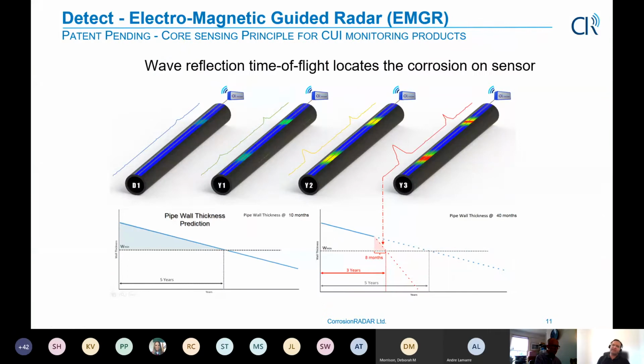The principle, as I mentioned, is electromagnetic guided radar, EMGR. It's a patent pending technique where the core sensing principle is, if you see this black cylinder as a pipe, we lay the sensor next to the pipe or near to the pipe or even embedded into the insulation. And on day one, you take a baseline, you see the signal here is not showing any indication, but over time, there are two locations where we start to see reflections. That's where either water is coming in, or in the case of the corrosion sensor, the corrosion is happening on the sensor,